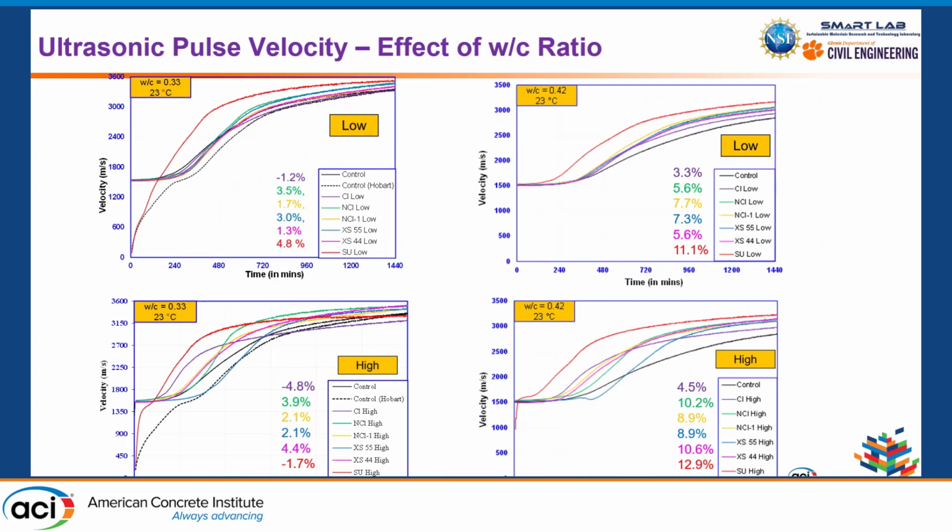Then we looked at ultrasonic pulse velocities of these cementitious systems. We used a particular mixing method where we can get a very particular liquid to solid transition in ultrasonic pulse velocities, and all the values from hydration kinetics and isothermal calorimetry had a very good correlation with the ultrasonic pulse velocity. So we think this is the best method to correlate the hydration kinetics to the physical transformation in the system from liquid to solid phase.